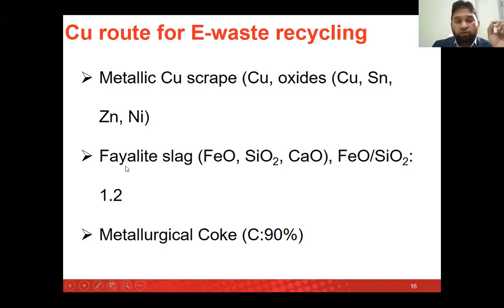Then you need to have a fayalite slag. Fayalite-based slag is used that contains iron oxide, calcium oxide, and silicon oxide. This is also called FCS slag. The ratio of iron oxide to silicon oxide is 1.2. And then we have the metallurgical coke, about 90% carbon. Of course, there are some other impurities in there.